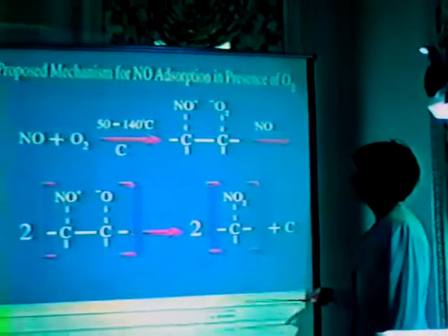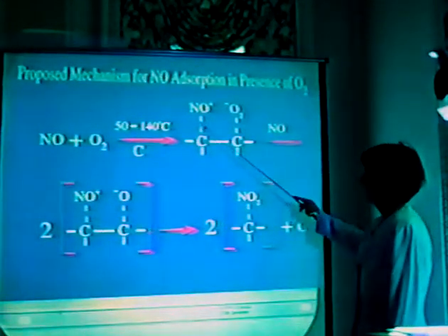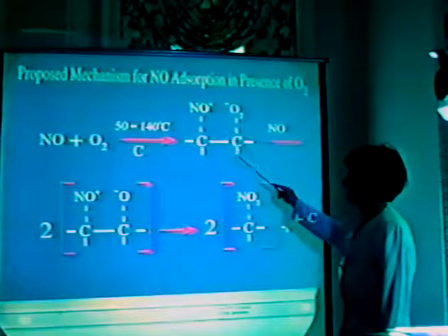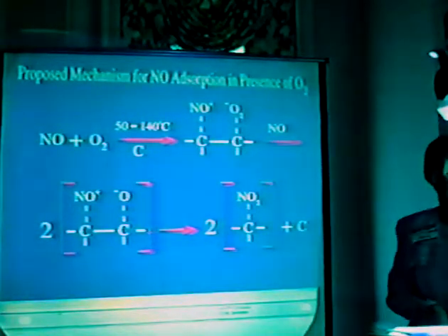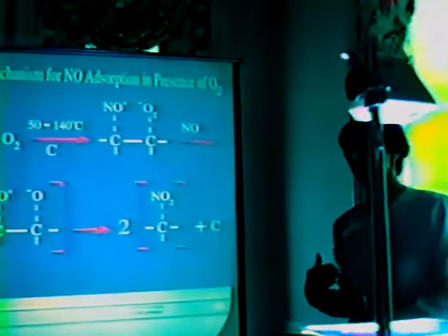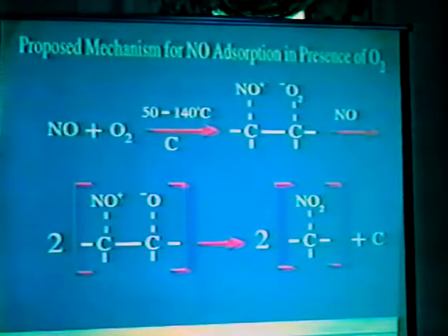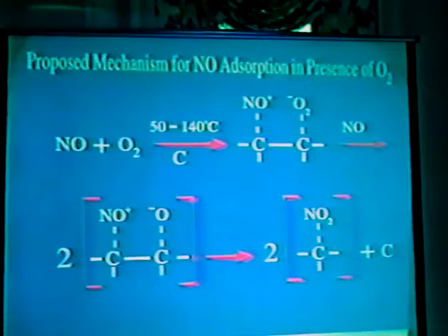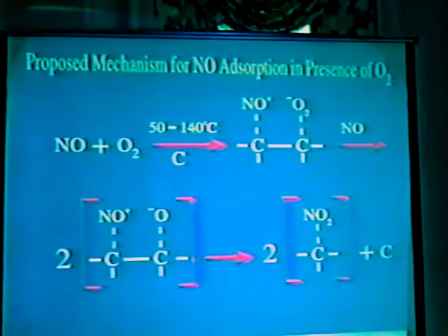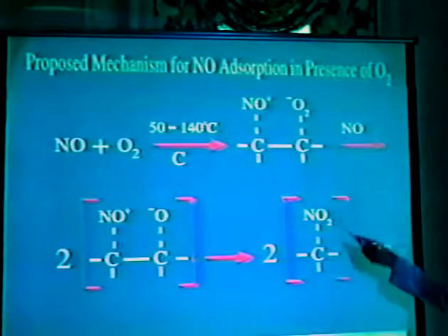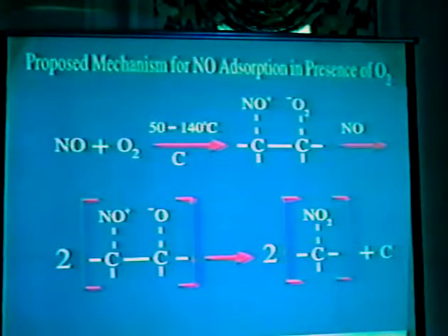However, what we can say is that in other systems, for instance, in the Mordenite system, an NO+ ion has been identified as stable. The NO+ ion has been identified by FTIR. And so what we would like to propose is the formation of ion pairs as a possible mechanism. Additionally, in the Mordenite system, this NO+ has been related to the conversion of NO to NO2.